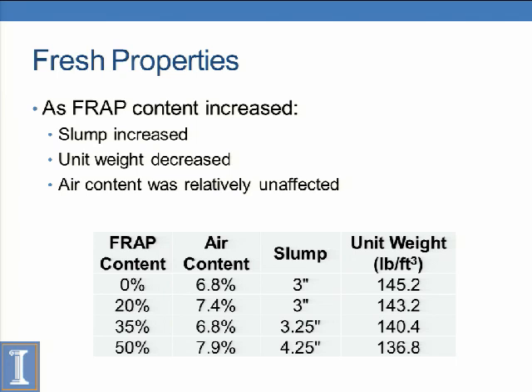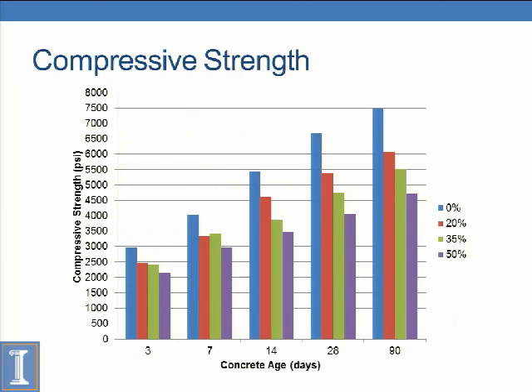Air content pretty much was variable. This is just for one of the mixes I did. Usually it ranged in about 6.5% to 8% typically, and that was a constant air entrainer dosage I used. So a little bit variability in the air due to the FRAP, but relatively I would say it was just unaffected. So now looking at the compressive strength, we have our 0,